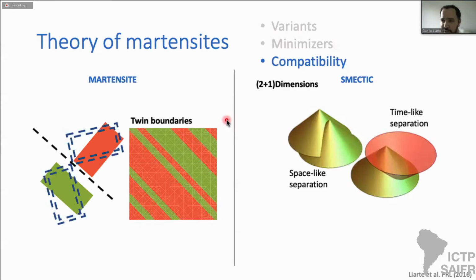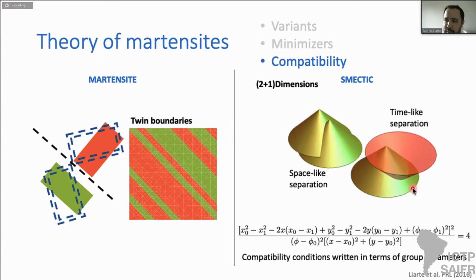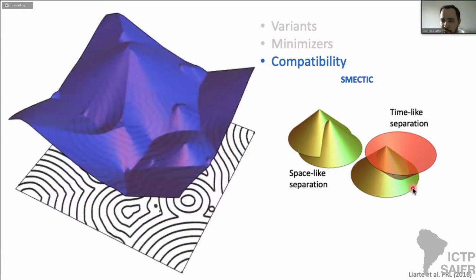Now, for the smectic planar sections, the variants merge via conic sections that are formed in the projection of intersections between conic surfaces. Now, if these epochs here, or the events, using relativity jargon, are space-like separated, the intersection will form a hyperbola, but only if they have the same sign. Conversely, if the epochs are time-like separated, the intersection will form an ellipse if the two cones have opposite signs. Now, I can write down explicitly what the equations for these conics are using the group parameters that I described earlier. And here is what a combination of these cones looks like for smectic simulations, with the layers of the planar section shown at the bottom.